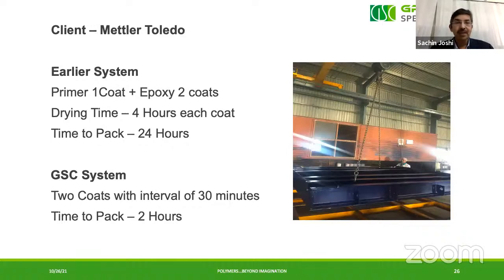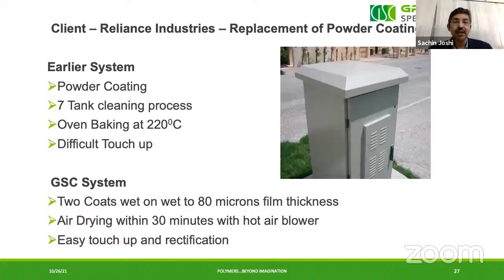Mettler Toledo, Switzerland-based company. All the metal structures, weighing scales, are being coated with this. Earlier, it was 1 coat primer, 2 coats epoxy. Drying time was 4 hours each coat, time to pack 24 hours. So the entire factory used to fill with the big structures. After that, only 2 coats of this coating, time to pack is 2 hours. So productivity increased by almost 300%.